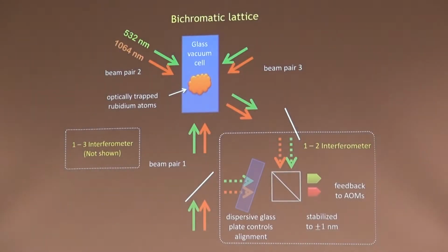Okay, so here's how we realize these Kagome lattices and other lattices in our laboratory. We have a gas of rubidium atoms, that's the particles that move within the lattice, and we expose these atoms to a triangular lattice that's formed by beams that come in within a plane from 3 directions at angles of 120 degrees from one another. But we make this optical lattice with light that has 2 different colors, where the ratio of the wavelengths that we use here is actually now exactly 2 to 1.